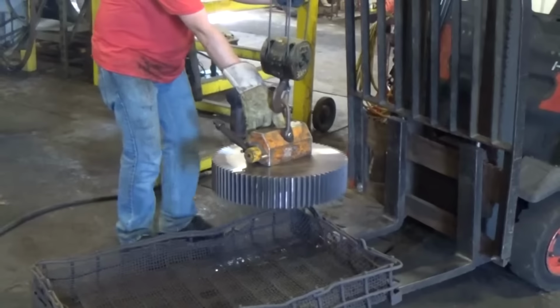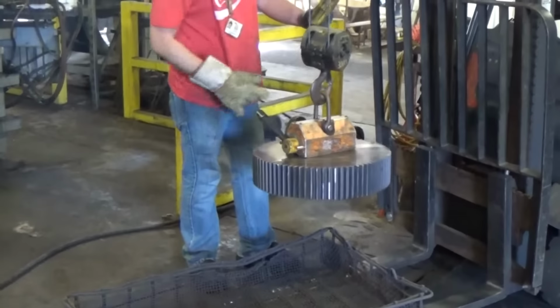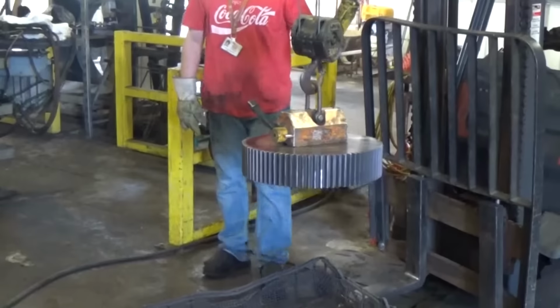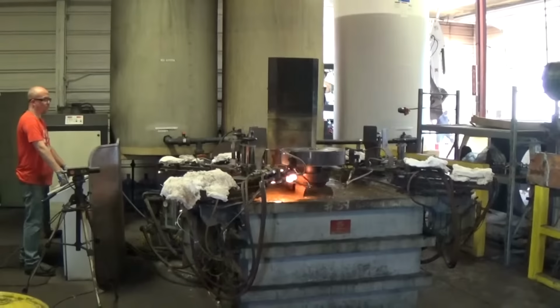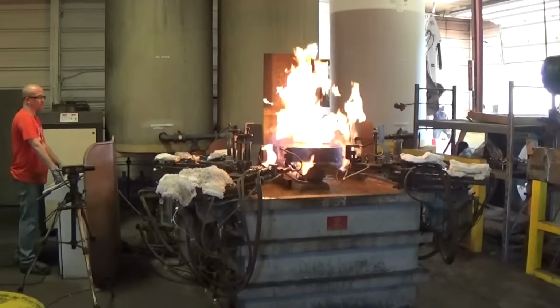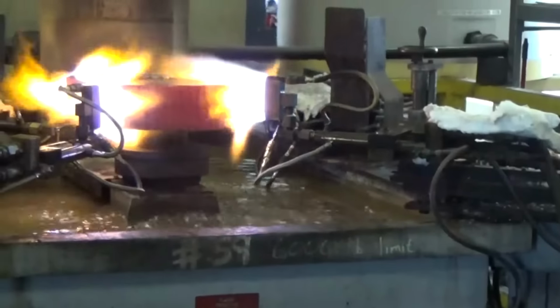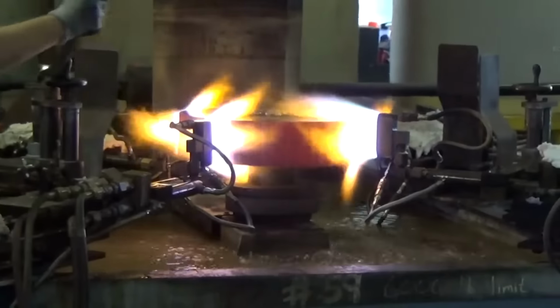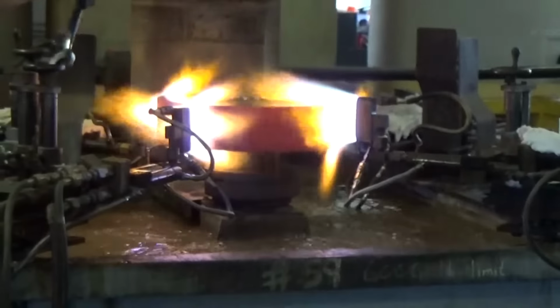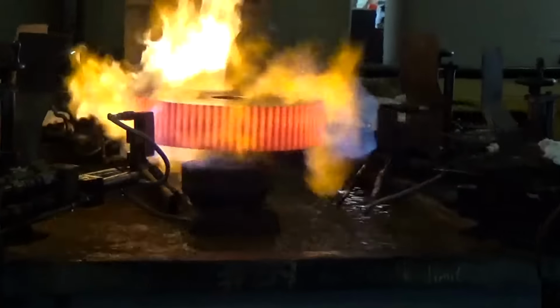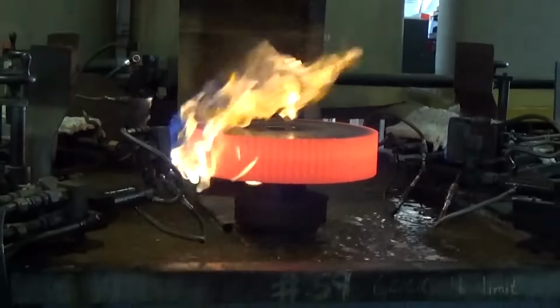In special cases where components only need to be hardened on an outside surface, an operation called flame hardening may be used. To do this, the part is loaded onto a spinning flame table where torches heat the outer surface to the desired temperature, usually 1600 degrees. An operator makes minor adjustments to the torches as the part heats.